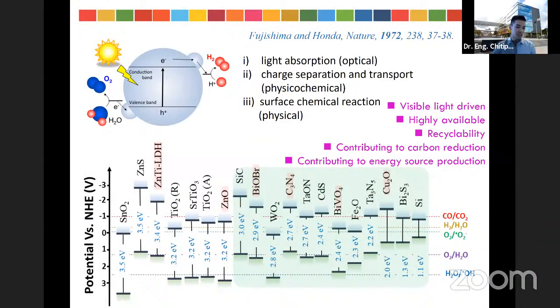Okay, so the energy band gap of the photocatalyst can distinguish the application, because if you want to do degradation of organic pollutants, for example, CIP, pharmaceutical waste, or some phenols, you need to think about the production of active radicals, for example, hydroxyl radical and superoxide radical. If the valence band top of the photocatalyst is lower than the required reduction potential for the generation of hydroxyl radicals, it can produce the hydroxyl radical. But if it does not match this level, it cannot produce this radical.